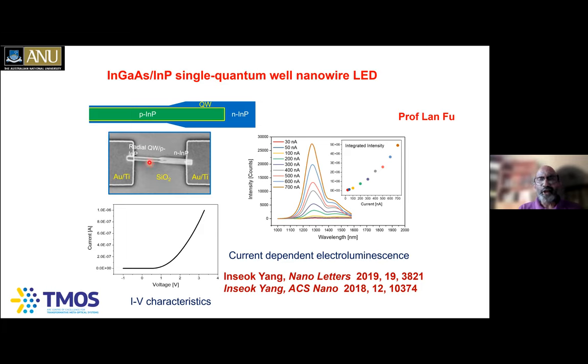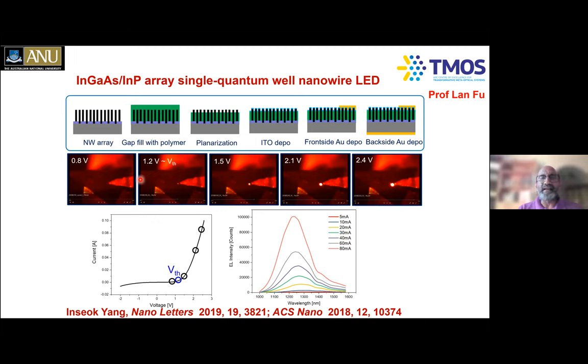So these are the so-called single nanowire LEDs, which are very useful for sensing applications and a range of other applications as well. But before Inseok Yang left our group, he also made the nanowire array LEDs. He grew the same type of nanowires, but instead in an array of ordered patterns. The challenge is how to make contacts with these nanowire tips at the top here. We deposit some polymer inside and then selectively etch the polymer to expose the tips using plasma etching, and then put some indium tin oxide, which is a transparent conducting oxide, put some metal on the side and the bottom and another metal as well, and then inject current and look at the IV characteristics.